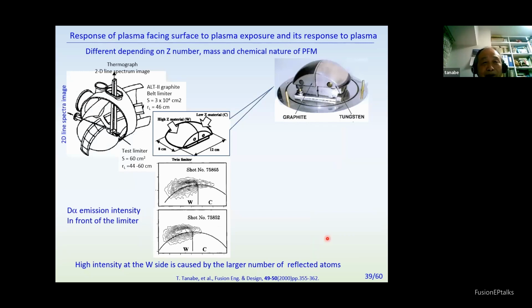This different response of tungsten and carbon is clearly seen in this experiment with twin limiters—graphite here and tungsten here—where we look at the line emission from this side. This is the intensity of the D-alpha emission in front of the surfaces. In tungsten, because reflection is large, the emission becomes high, whereas for carbon the reflection is small.